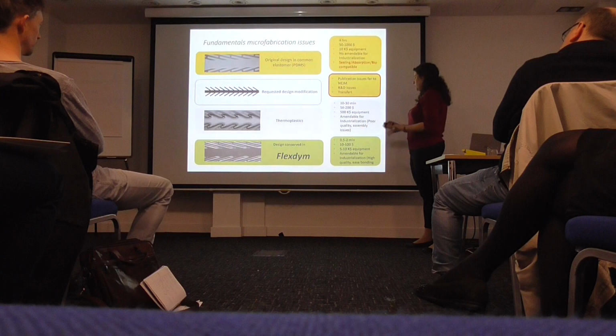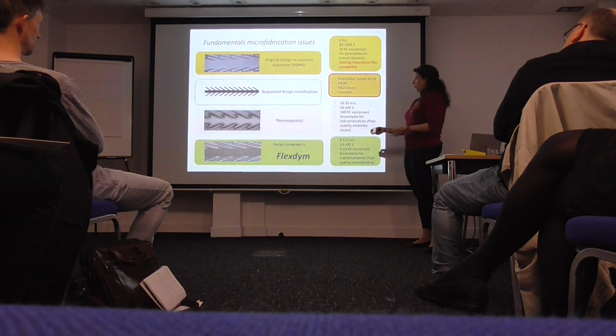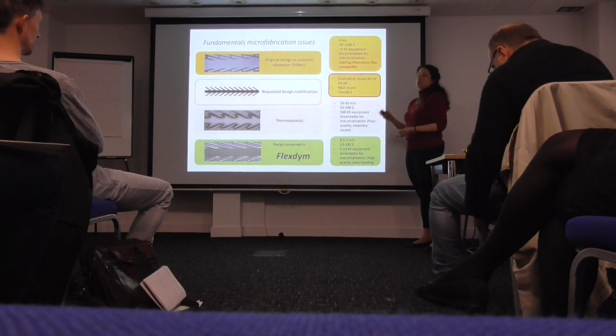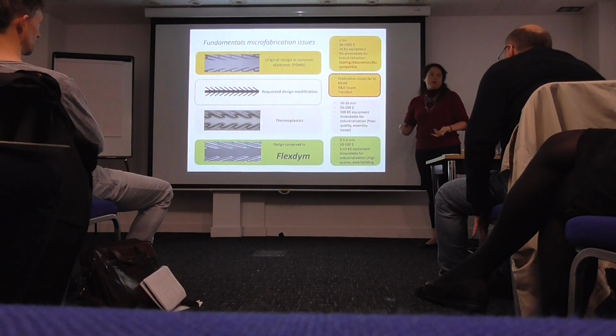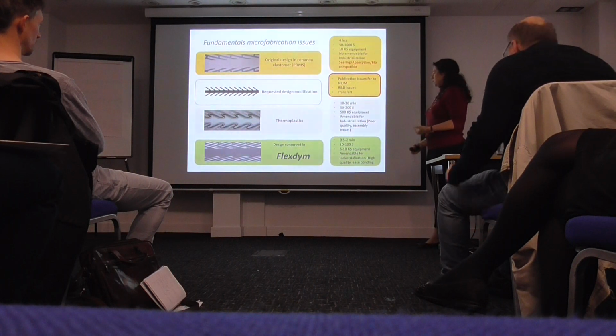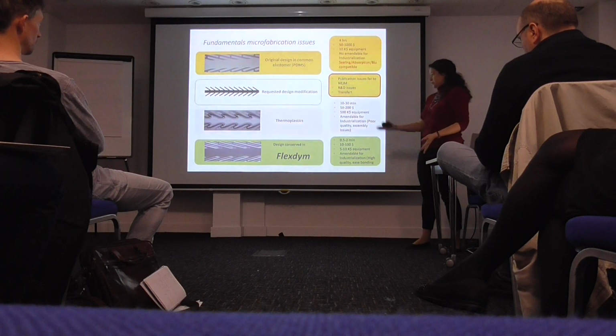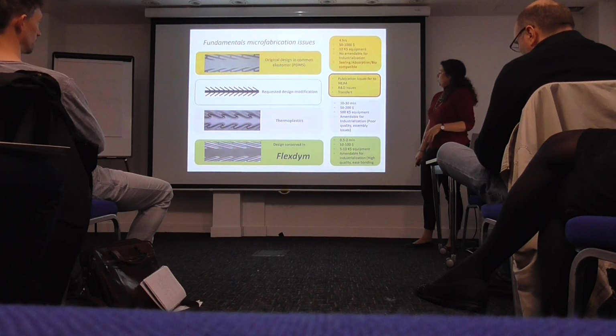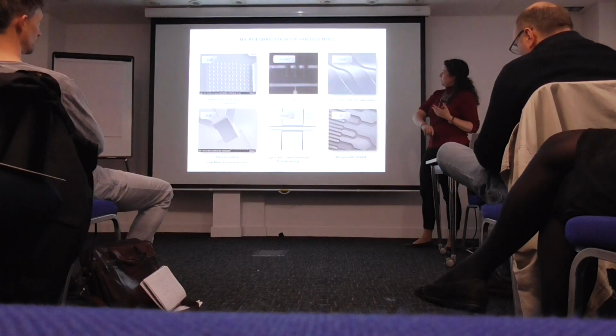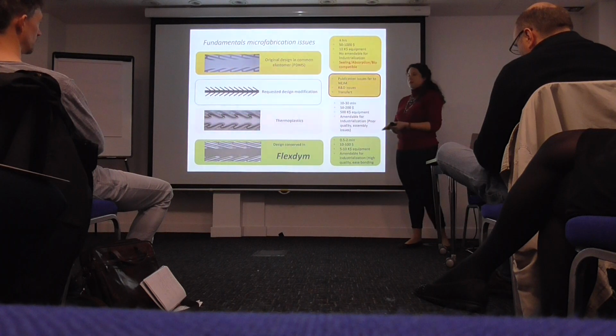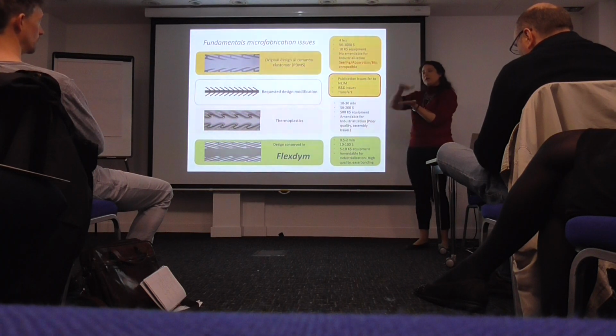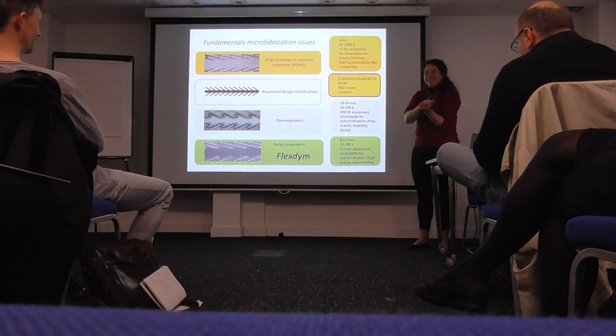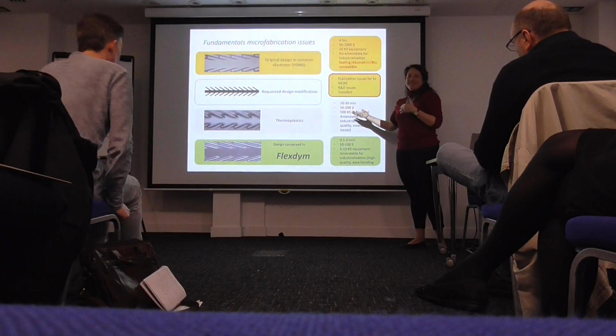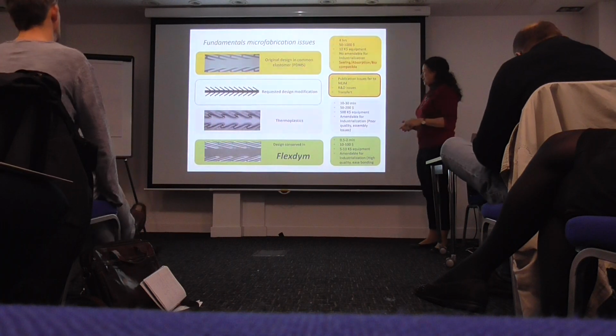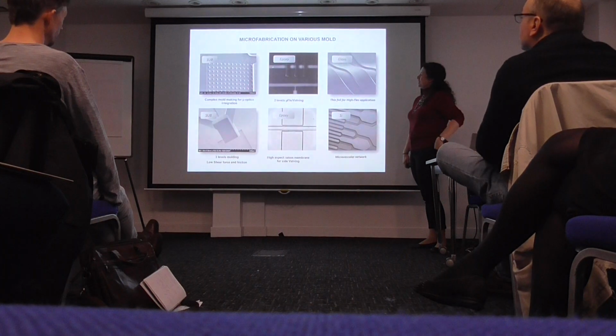The advantage is that by doing 150 degrees and low pressure, we have the same resolution as PDMS. We knew we needed to hit that, because if we wanted the labs to start integrating that into it, we needed to match that property of the PDMS. So we're quite happy because it does it very nicely. The problem was that not a lot of labs have, I mean, you can do it on a hot plate and put a couple of books on top of it that would apply a pressure, but it's not really professional. So we needed to develop a machine, and you're going to see the machine that we developed, because obviously that wasn't too nice as demonstrations that we were doing.